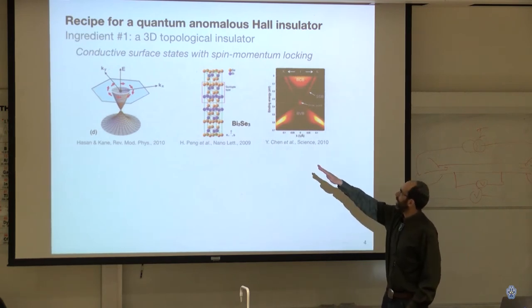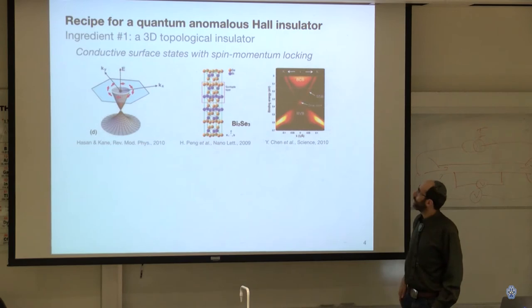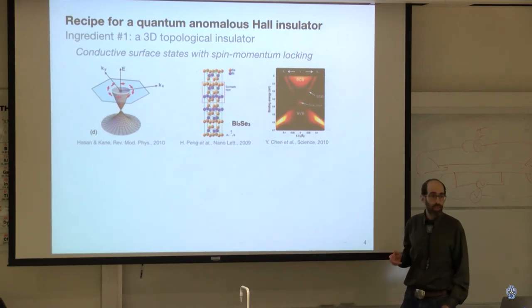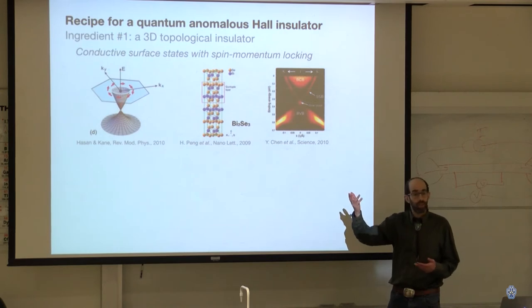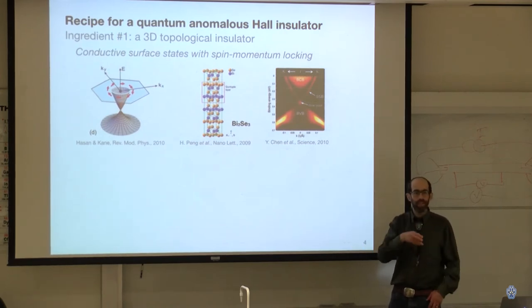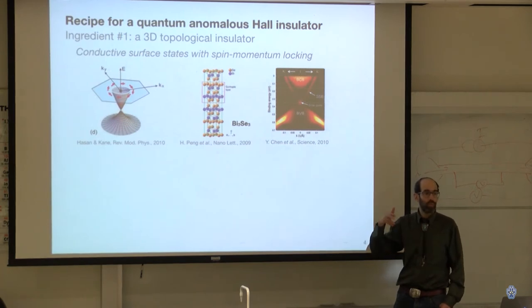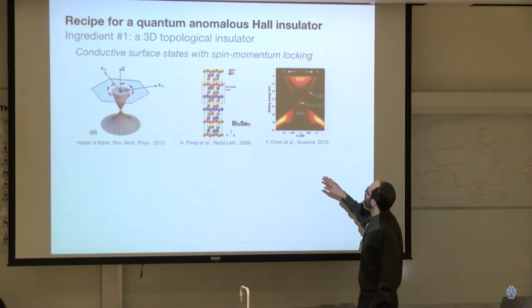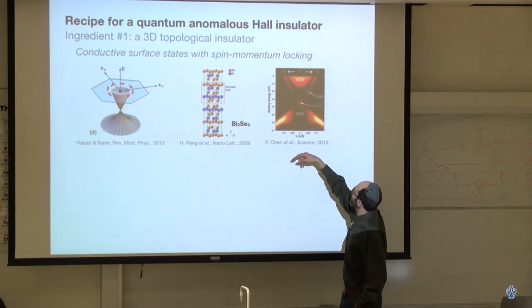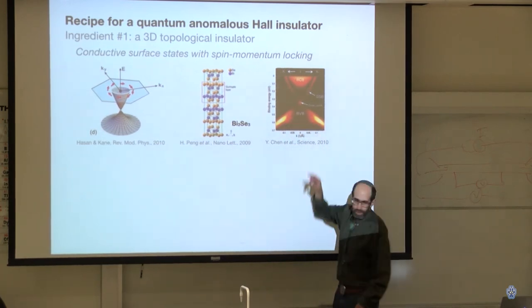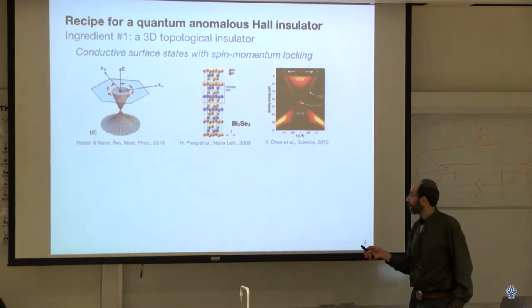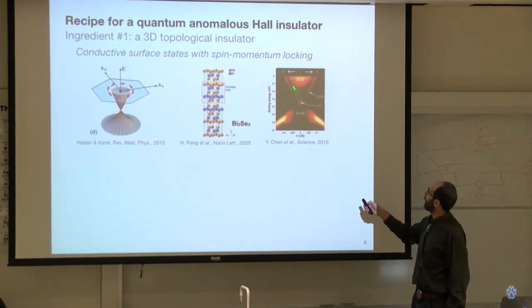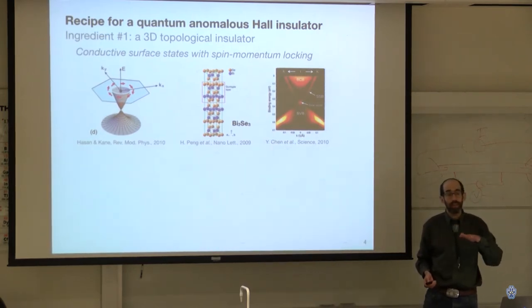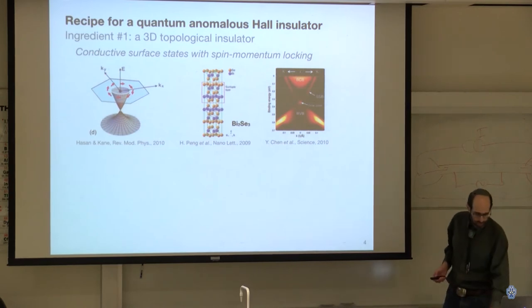So if you look at the electronic states of this system, what I'm showing on the right-hand side is from what's called a photoemission measurement, that you use light to knock out electrons, and by seeing what light you needed to use and where the electrons fly out, you can tell what the states of the electrons were. And so this is what's called momentum, and that's energy, and there are states down below that are called a valence band, states above that are called a conduction band, and then in between, if you look closely, you can see that there are states that connect the two, and those are the states that live at the surface, the top surface. So that's the first ingredient.